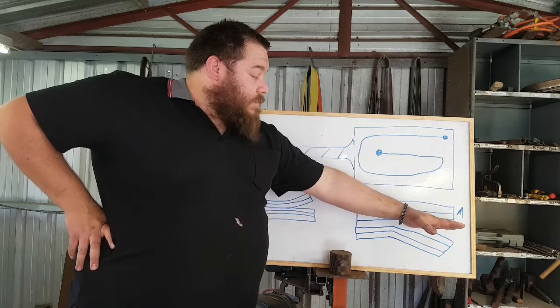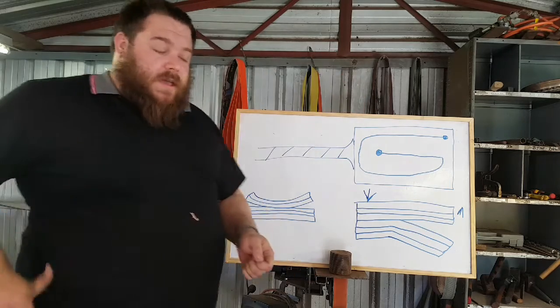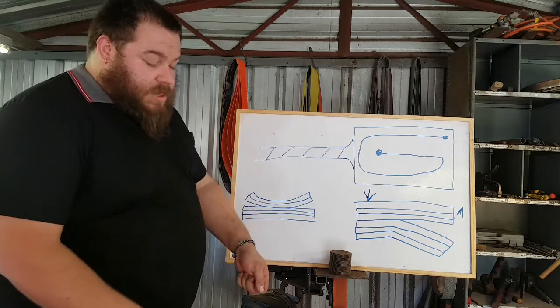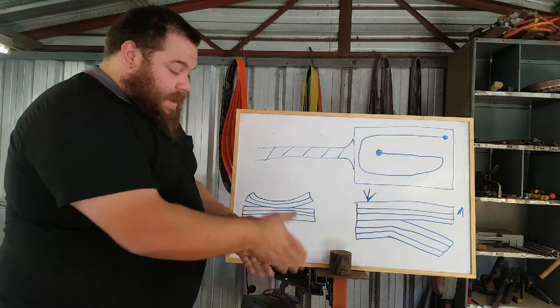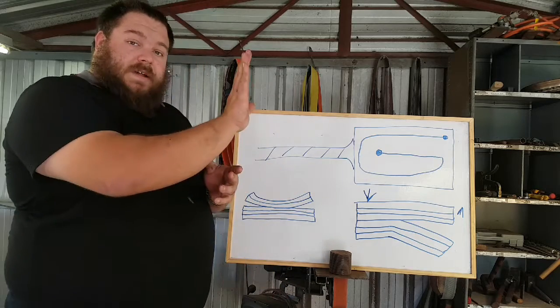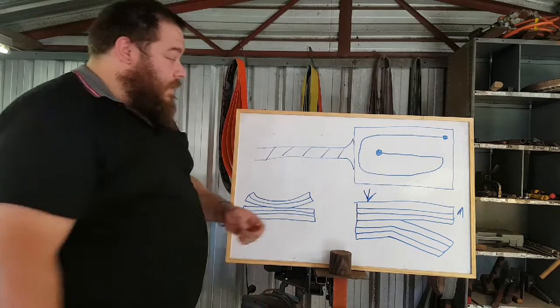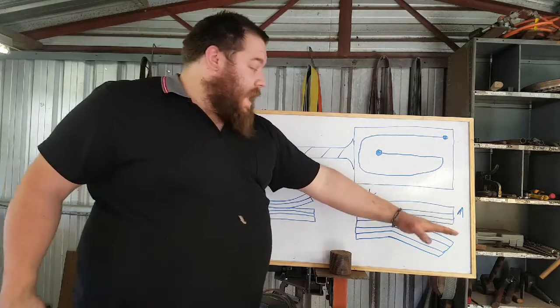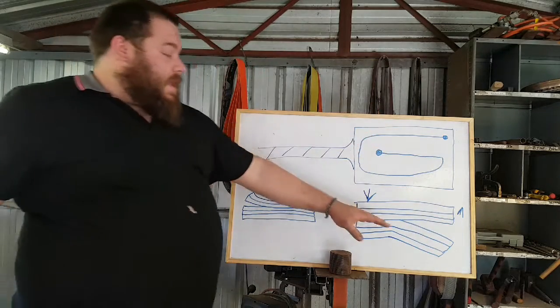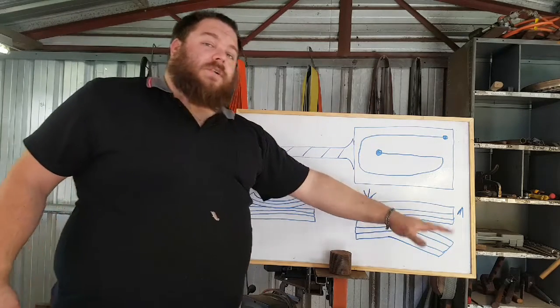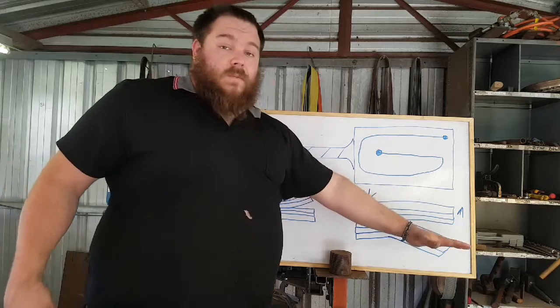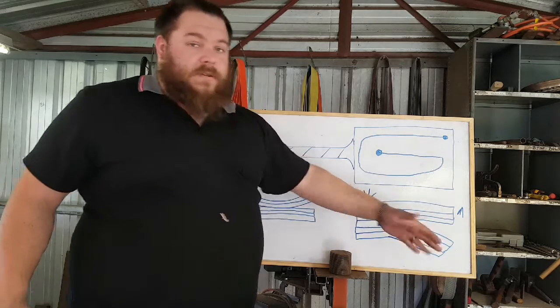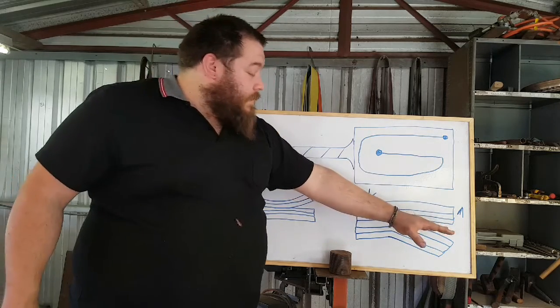And it sheared the weld by flicking that toe up. If anyone's ever put a piece of material over the edge of the anvil and hit near the anvil, you'll notice that the tip tries to flick up while the piece you're hitting goes down. That's exactly what happened here, is that end tried to kick up, whilst the piece that was in contact with the anvil wasn't under as much strain, so it just stayed where it was. Well, this is bent down, but actually, realistically, it's actually flipped the other way.